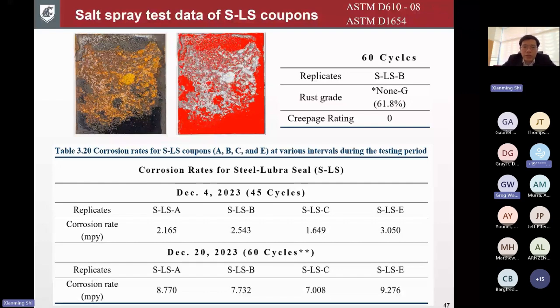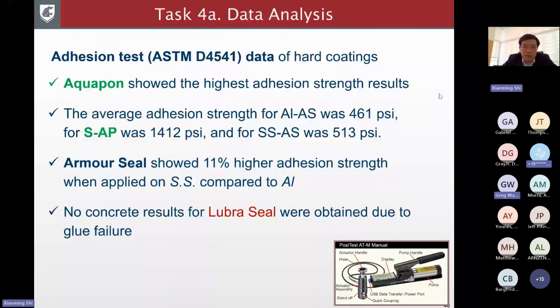As a summary of the data analysis, if we also look at the adhesion test, Aquapon, which is the zinc-rich primer, showed the highest adhesion strength. Keep in mind, the Lubra Seal and Armour Seal were just sealants, so not very strong coatings. In this case, the Aquapon adhesion strength on average was more than 1,400 psi, while the Armour Seal on aluminum or stainless steel was around 400 to 500 psi. Now, for the Lubra Seal, one challenge was that the glue didn't work well on the substrate, so we couldn't get good results.